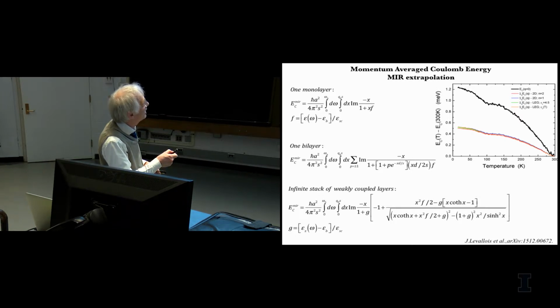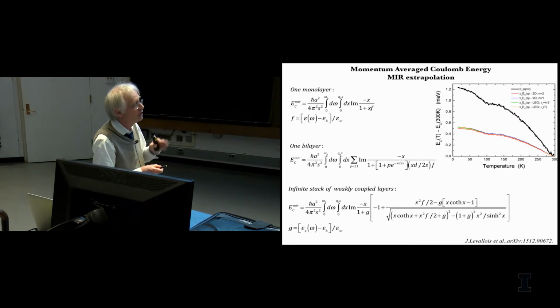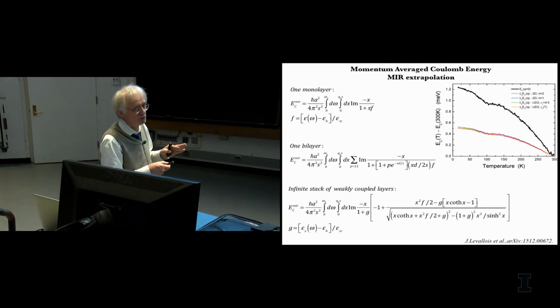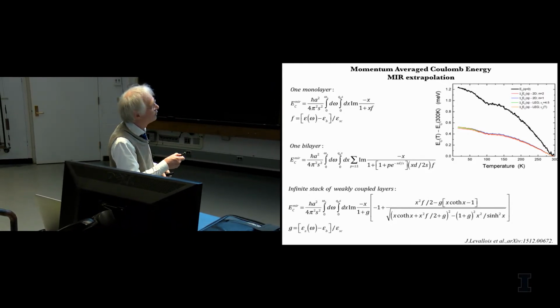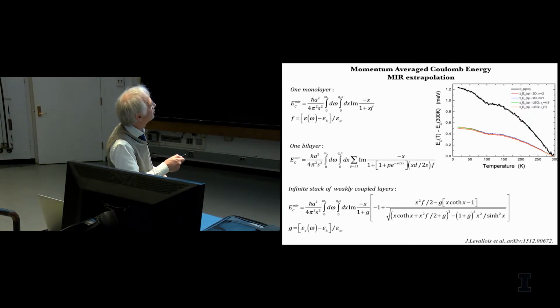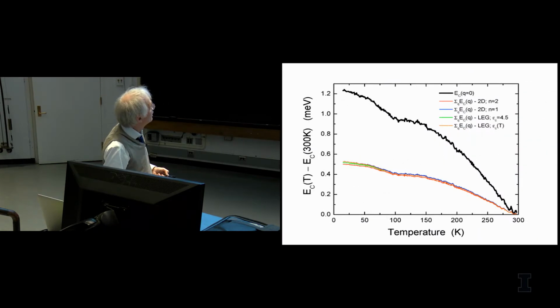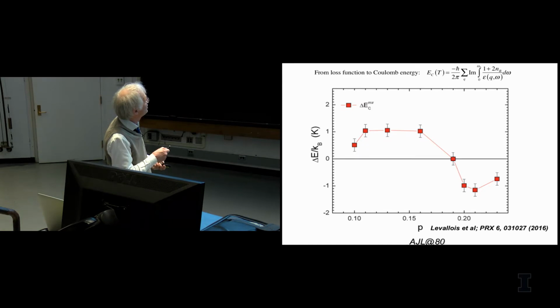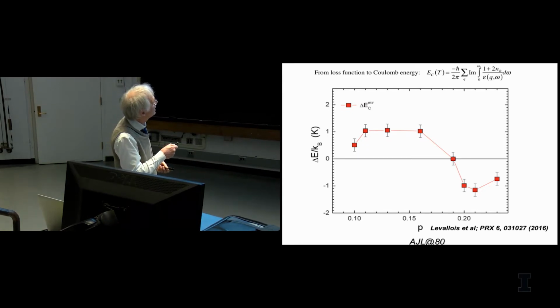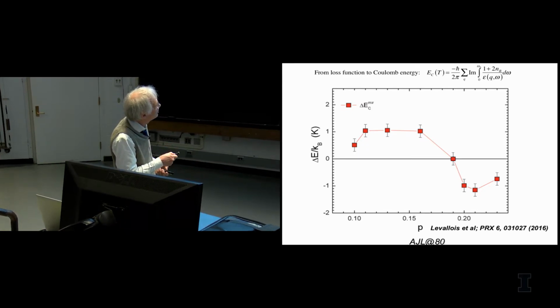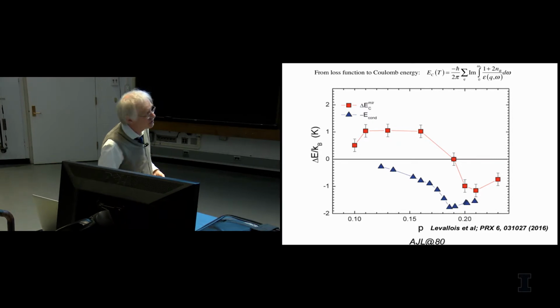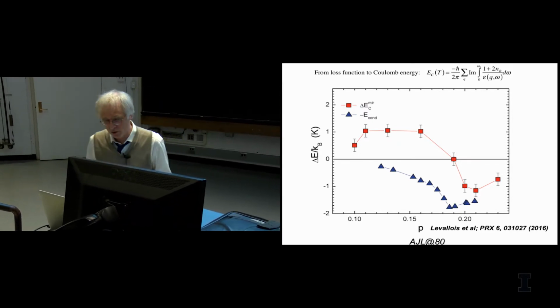So this is what you would get if you assume that all Q values in the Brillouin zone have exactly the same value as what we measured. This is what you get if you assume you have this inverted hat shape. So you get about 1/3 or so of the maximum estimate. And doing that for all these different dopings, this is what the Coulomb energy looks like. It's increasing for the lowest doping, and it is decreasing below Tc for the overdoped samples, and there's a point where it doesn't change. And these are the corresponding condensation energies from John Loram's work.